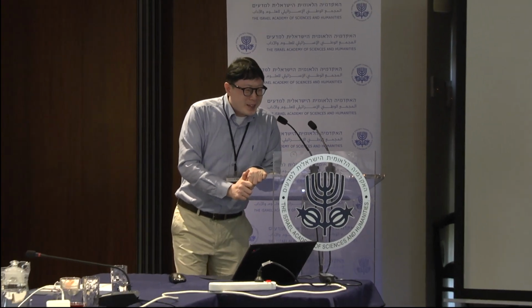The second part is why the proximitized superconductivity is really strong on this bismuth film. We don't understand that at all, but somehow it is transparently proximitized through the edge state. I'm not sure this is a good way to explain it, but personally I think there's no strong way to break the superconductivity only along the edge states. Yeah, this is the only thing I can tell you. Your topological state protects such a strong effect. It's not complete, but at least it is very robust in our sense.